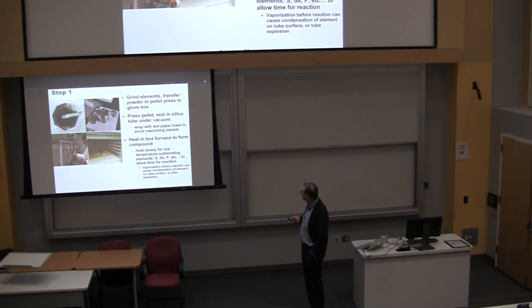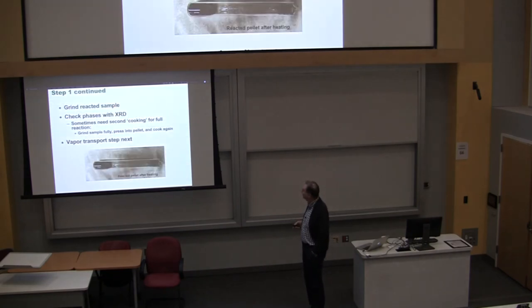So you want to go slowly. Whenever you're working with things like sulfur and selenium and phosphorus, you don't want to heat it up too fast. Heat it up too fast, and your tube will explode. You don't want to volatilize stuff. You want it to react first, and you want it to react slowly. So you basically want your nice stoichiometric powder before you get started with the vapor.